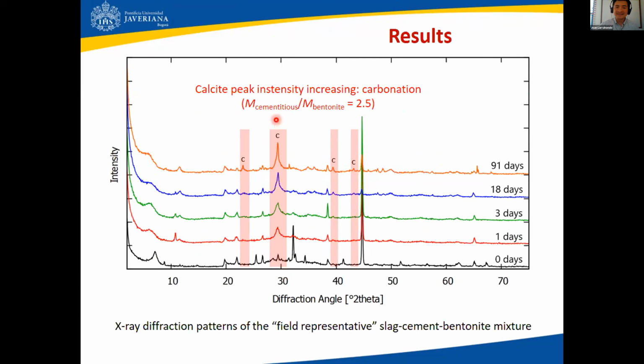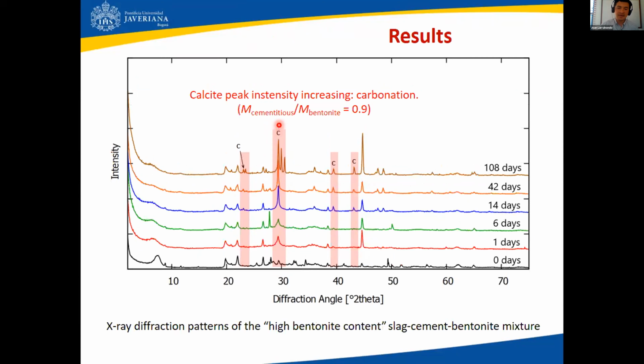Now, if we look at the same patterns that we saw before, but with a different mineral in mind, that is calcite, calcium carbonate specifically, we confirmed the presence and enhancement of calcite over time. So you can see here clearly that from 0 days up to 3 months, basically you get sharper and very distinct calcite peaks. This happened not only in the field representative sample, but also in the spiked high bentonite sample.